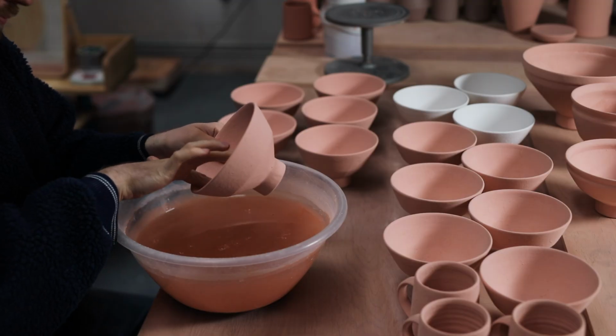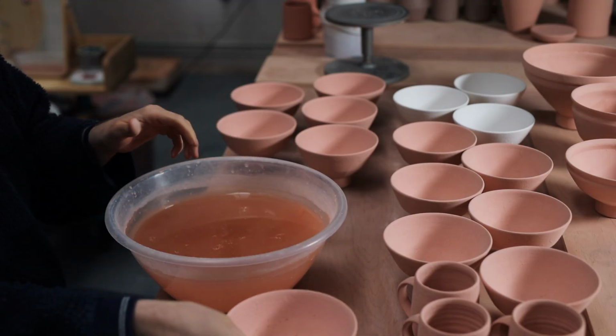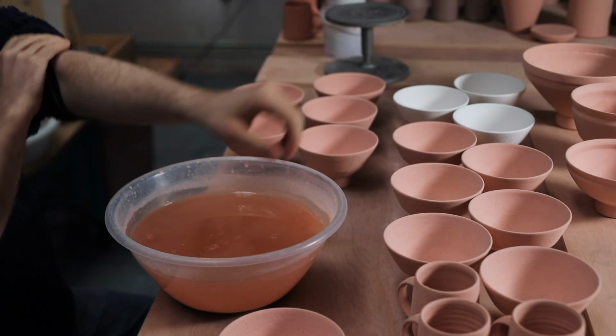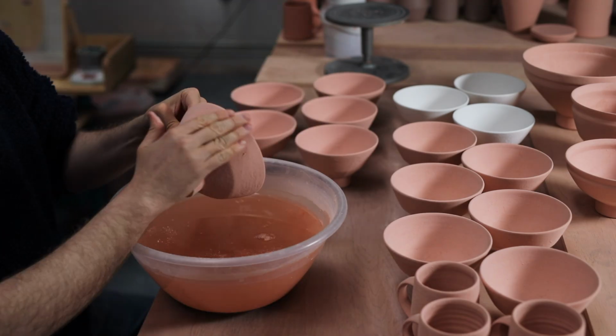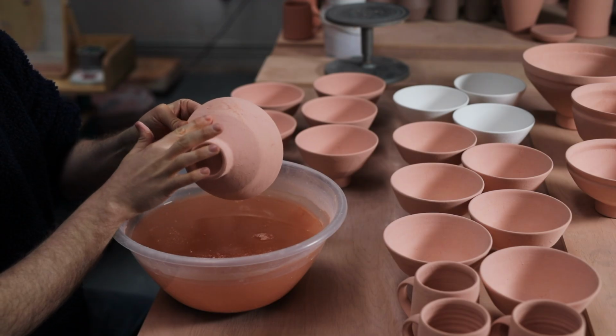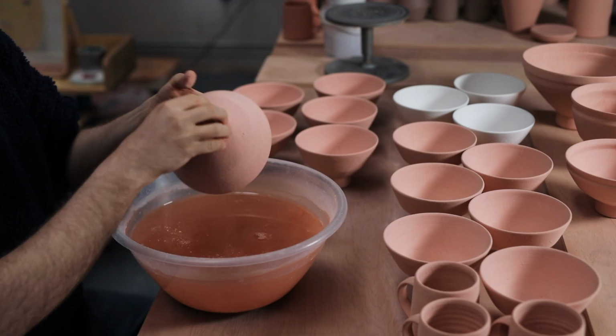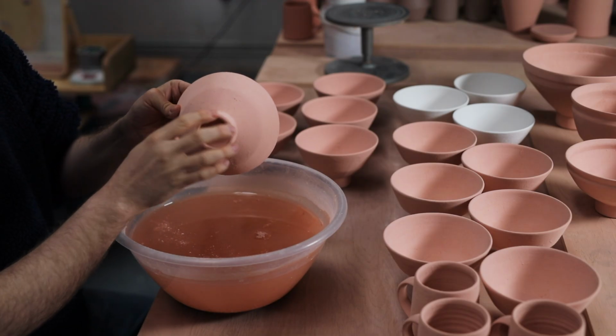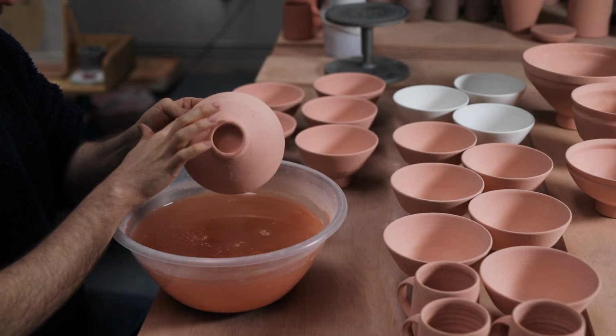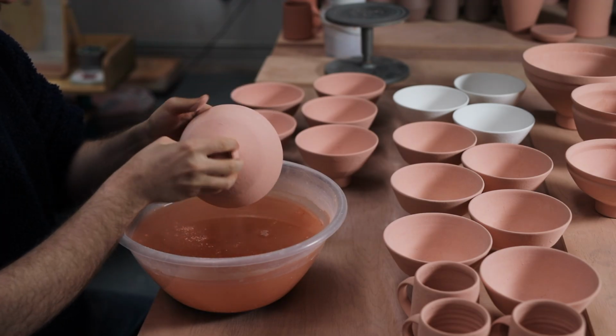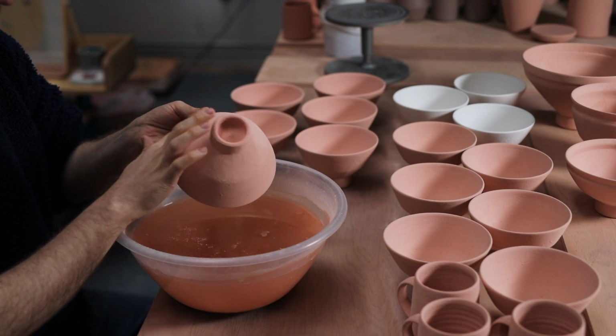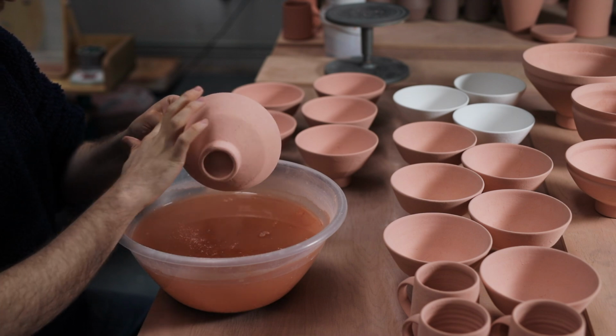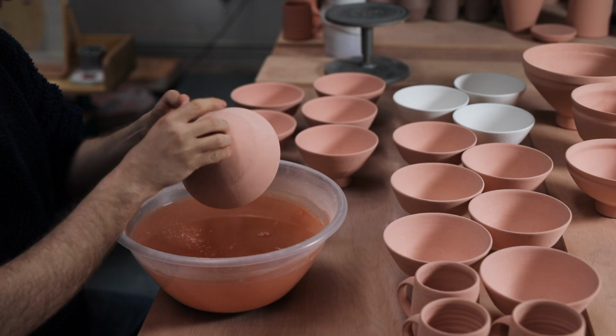The next step is to tidy up the surface of these. I begin by gently rubbing over the tong marks, grinding back the excess glaze that tends to pile around the metal prongs into a flush, smooth layer. It's also at this stage that I rub over any thick drops on the surface, whilst simultaneously being very careful not to make any thin spots, as those will show once the pot has been fired. And once again I'm working over a basin of water, as this will collect much of the glaze dust, which I can then of course recycle.